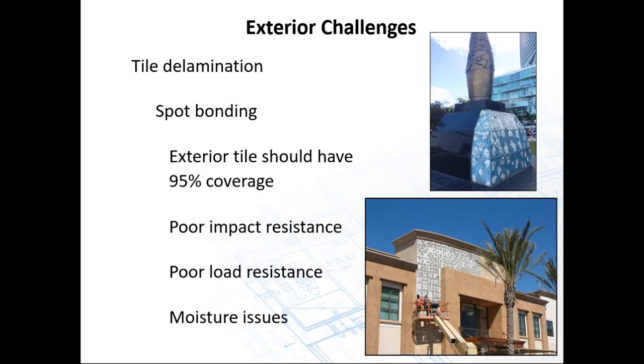As we did further investigation, we found that the flashing wasn't done properly, and then during the rains, water was getting in. When we started removing tile, the stone, we found that spot bonding had been used for the installation system. So what was happening is during the rain, the wall cavity was filling up with water, causing the stone to look dark. And then after the rains went away and it would start evaporating out, it went back to its right color. Needless to say, the whole job came down to not being properly installed. So spot bonding is not a method to be used, and we should stay away from it.